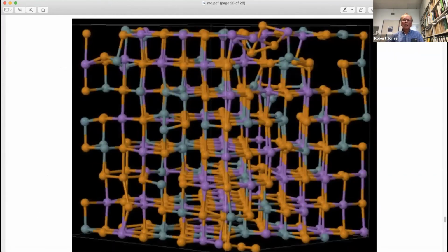Now, I go to the second last slide here. And we see, if we look at this structure in detail and we compare with experiment where it's available, we do see that vacancies tend to collect around the tellurium atoms, and germanium moves away from vacancies. And remembering that more than half of the atoms here are tellurium, basically the lowest energy in this simple picture is obtained by a structure closely related to the one suggested by Yamada. I repeat, I am not saying that this explains everything. It gives us a way of thinking about these problems where we could maybe say silicon is not as good as germanium, or phosphorus is not as good as antimony, and understand why, without doing a calculation that takes 2 years.